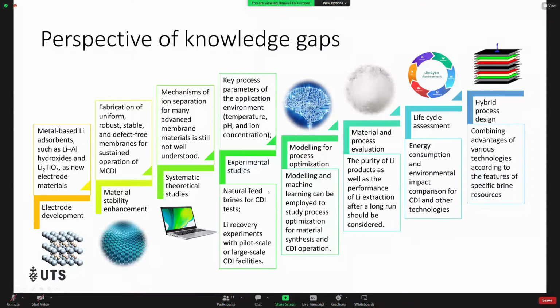Since most of the previous studies are using simulated brines, more natural feed brines should be tested using CDI. And there's no lithium recovery experiment with pilot scale or large scale CDI facilities. For process optimization, modeling can be a useful tool. And for evaluation of the material and process, we should consider the purity of lithium product and the performance of lithium extraction after a long run.